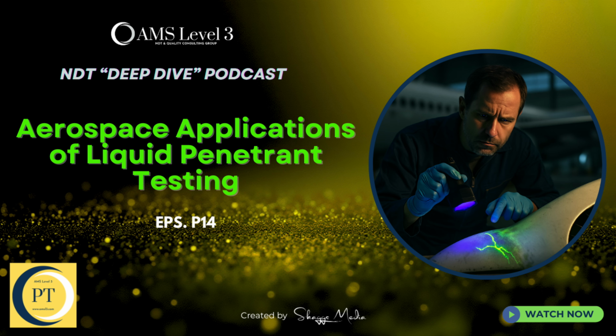Oh, absolutely. Overwashing. If you're using a manual spray, the water pressure is strictly limited to prevent it from physically eroding the penetrant that's sitting inside the crack. And what is that pressure limit? And what happens if you go over it? The pressure can't exceed 275 kPa, which is about 40 pounds per square inch. If you exceed that, or you just spray for too long, you're overwashing, and you literally wash the penetrant out of the discontinuity. You're washing away the evidence.